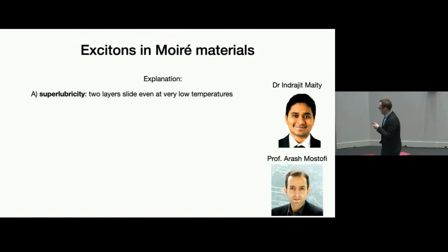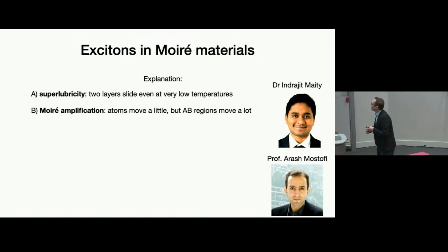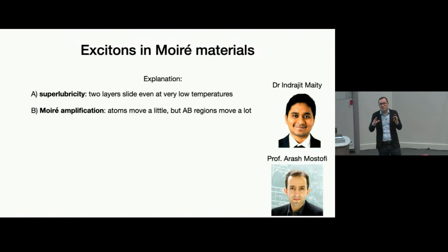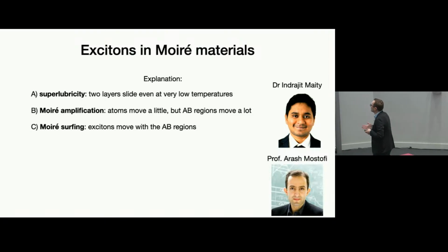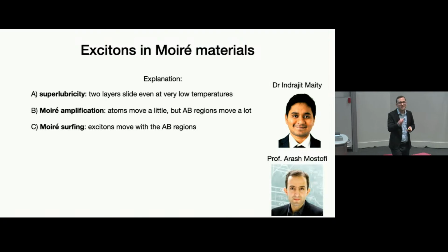And this is the work of Indrajit Maity, who was a postdoc in my group, and also he worked with Arash. And to understand what's happening, we have to, again, think about the three things we learned about the moving Moiré patterns. The one thing was superlubricity. It requires basically very little energy for the two layers to slide, so they can do that even at very low temperatures. The second bit was Moiré amplification. Even if the atoms only move a little bit, the Moiré amplification means that the AB regions move a lot. And then the third bit was the Moiré surfing.